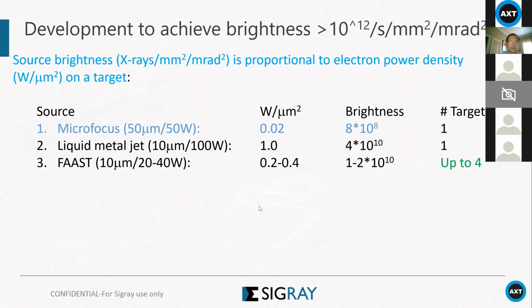Just compare what is commercially available with what we have. A microfocus source, commercially and widely used, is 50 watts over a 50 micron spot. So the most important is the watts per square micron. That's really related to how bright the X-ray source is. And there's a microfocus, then the liquid metal jet, as you can see, and there's our source.